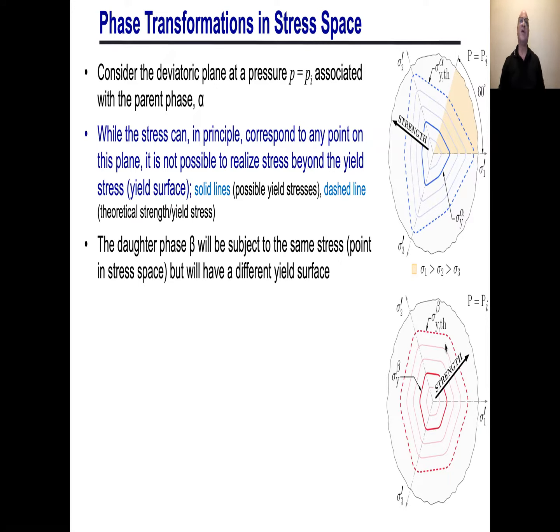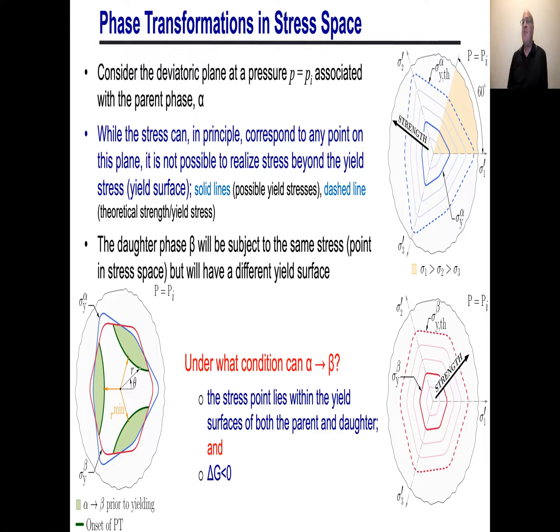Okay, now, if I know those two things, I can say, what is the condition for a transition from an alpha phase, an alpha grain, to a beta grain? It's actually quite simple. We need 2 things. We need that the alpha crystal, at this stress state that we're talking about, sigma, lies within the yield surfaces of both the alpha and the beta phases. So what I'm showing on the left is the yield curve for a particular level for phase alpha in blue, and the yield surface for phase beta in red. Any point that is accessible has to lie within both of those yield surfaces.